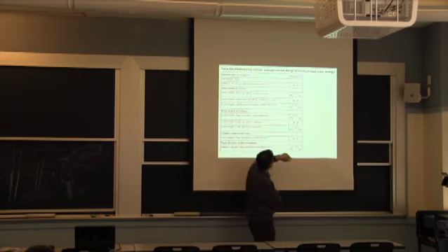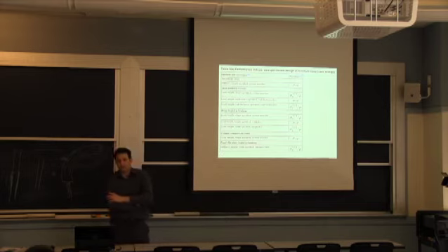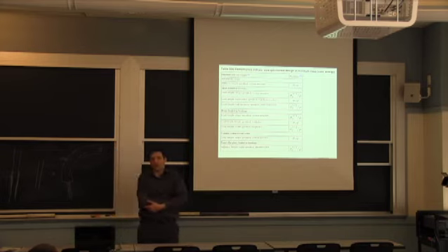If the strength is more important, that's a situation where you may still want to use steel, even though it's a higher density. So you have to think a little bit if you're doing a design in tension or compression. And that's what I was faced with when I looked at those titanium ribs, where at least 2/3 of the design was more for compression and buckling than it was for strength. So going from titanium to steel was really not a great option. The only advantage that the steel could provide, and that was even possibly, was for the tension part. Everything else was better off with a material of lower density that you make thicker, that's more resistant to buckling.